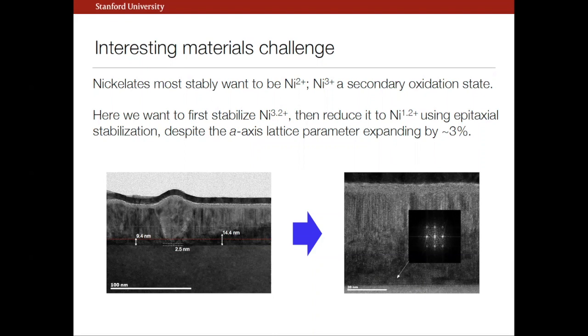So it's quite a complicated and rather fascinating system, I would say. To just give you an idea how the starting point was, this is a cross-section of that kind of sample in the early days. You need to have loving eyes, but it turns out this first 1 or 2 nanometers was this infinite layer phase that we will eventually argue is the superconducting phase. You can see it's a mess. It's segregated, it's falling apart, all sorts of crazy things happen. And so after a bit of work, we got to the case that we could stabilize a few nanometers thick of this infinite layer phase. You can kind of see that by the Fourier transform. This elongation in the Fourier transform is indicating that we've compressed the C-axis by deintercalating the oxygen. So this kind of sample does show a complete zero in resistance, but still, who's to say what of all of this is superconducting, right?